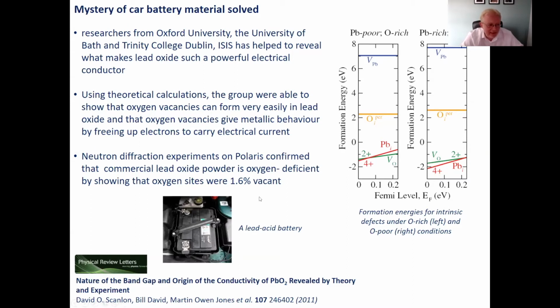And we calculated 1.6% vacancy from the observed Bragg data, and that correlated extremely well with their calculations. And so we were able to show that their calculations were actually correct, and these materials were non-stoichiometric to the level that they indeed had predicted.